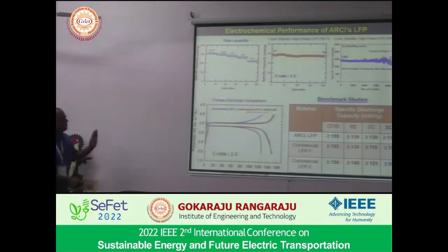Then this is the benchmark. We always compare with the commercial material. The black one is the ARCI material performance. This is the typical charge discharge profile of LiFePO4. If you can see, the discharge capacity at 1 C is about 139 milliampere hour per gram. The commercial one is equivalent to our ARCI material, and we are better than the other commercial material. But if you go for fast charging at 5 C rate, our material could deliver more than 110 milliampere hour per gram, whereas the commercial material delivers less capacity. The reason is we prepared nano-size particles with a good carbon coating and all.